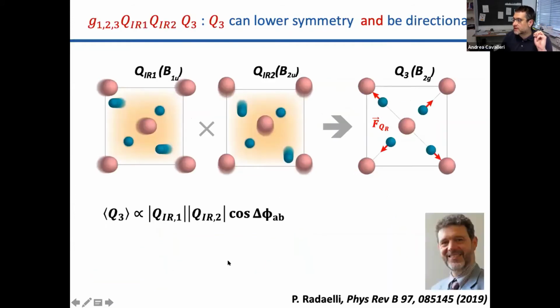This was actually something that was proposed to us. It was raised by Paolo Radaelli when he was a sabbatical visitor with us. And the point that Paolo made very aptly was that there's two good things if you start pumping only one phonon and look at what happens to the second phonon. But if you pump two and look at what happens to a third, firstly, the idea that the third phonon can only be totally symmetric is no longer true. If you know as much group theory as Paolo knows, you'll know that if you take a B1u mode and you multiply it by a B2u mode, in certain cases, you will have a distortion along a mode that has a lower symmetry than the totally symmetric one.